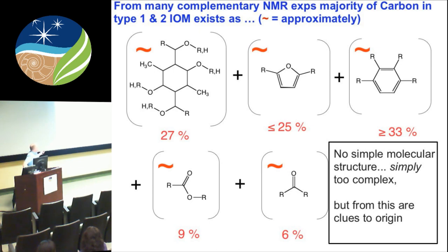With many, many NMR experiments over many years and a huge selection of organic matter from different meteorites to study, we found for at least Murchison, about 27% of the carbon is represented by highly branched aliphatic carbon, highly substituted. About 25% is furanic structures, 33% very small aromatic rings, very highly substituted, maybe 9% carboxylic groups or esters, and about 6% ketones. There's no way that I could draw you a unique structure based on this. This is as good as it gets. Although people will publish these in the literature and say, oh, this is the structure of IOM, it's ridiculous. But within this, there are some significant clues to its origin.